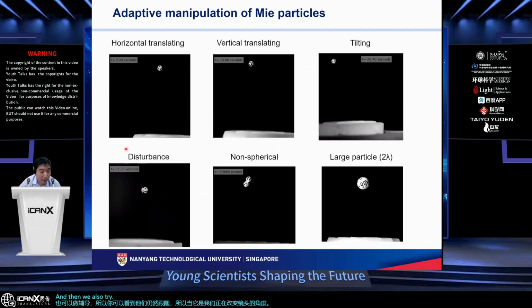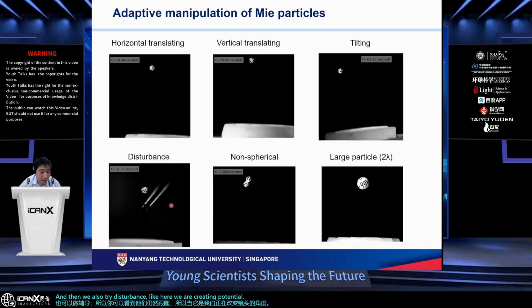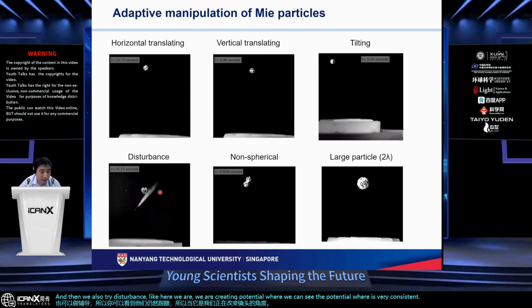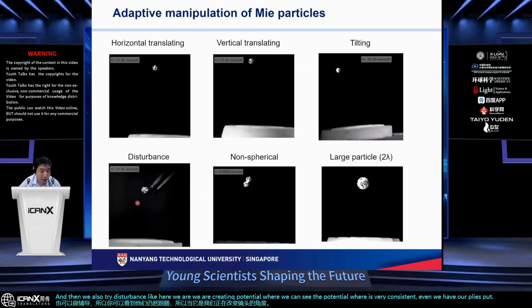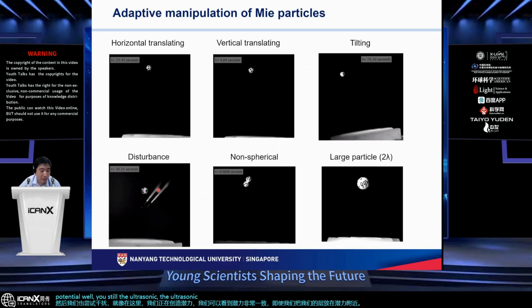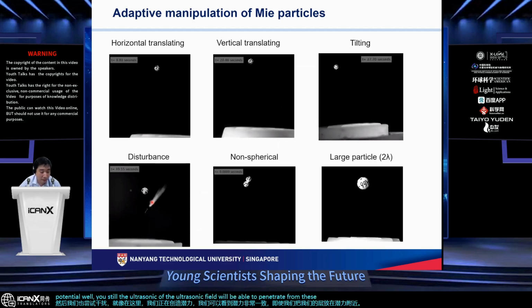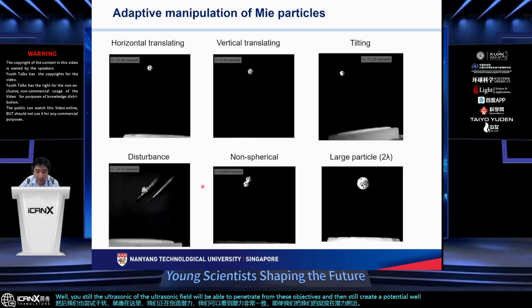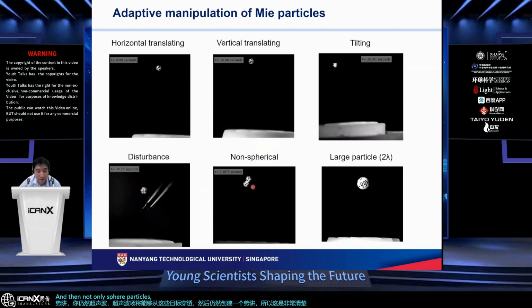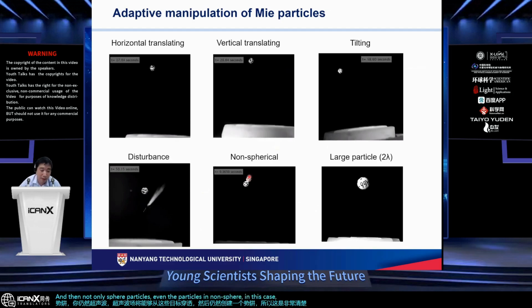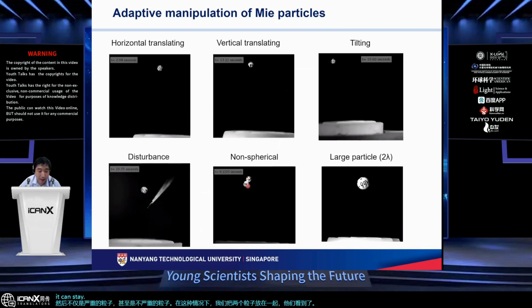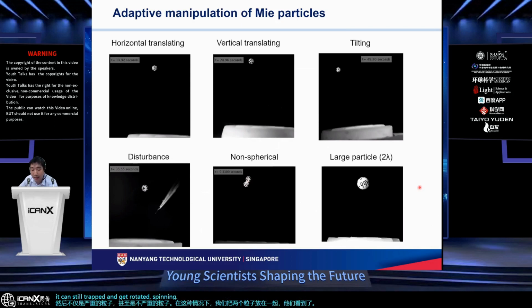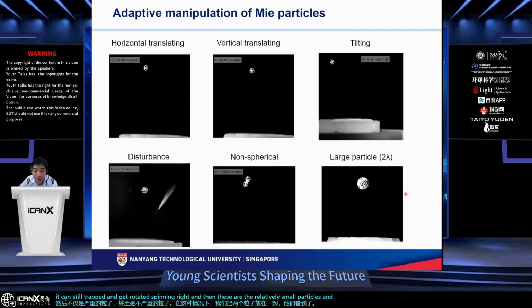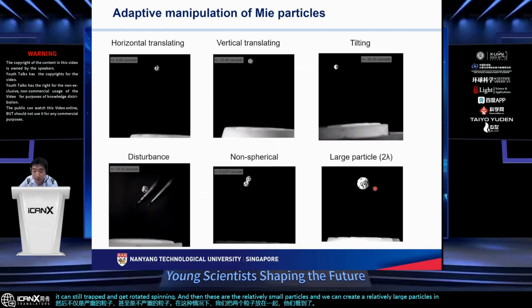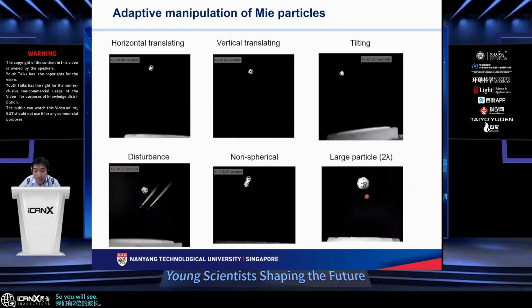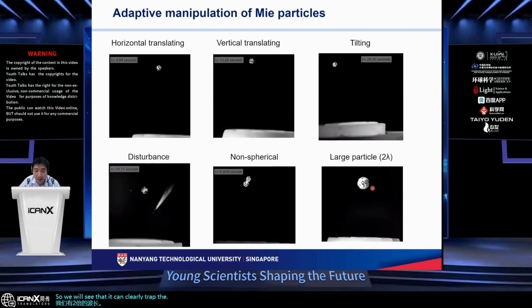And then we also try disturbances. Here, we are creating a potential well, and we can see the potential well is very consistent. Even when we put objects near the potential well, the ultrasonic field is able to penetrate through these objects and still create a potential well. So this is very clear trapping. Not only spherical particles, but even non-spherical particles. In this case, we put two particles together, and you see that it can still trap them and they rotate, spinning. These are relatively small particles, and we can also trap relatively large particles, about 2 times the wavelength, and it can clearly trap even a very large particle.